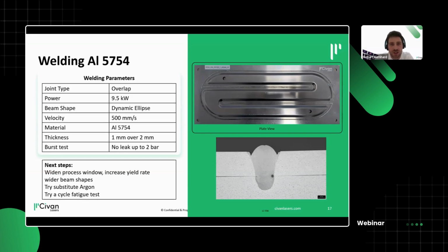So there are, of course, some challenges to overcome at these high speeds. And I would argue that we can even widen the process window to get rid of undercuts. But in general, it's really important for us to have the leak tightness, and this is what we are able to achieve with this parameter set. I'm of the opinion that we can also do construction or structural welds as well, but the leak tightness here, the long welds we need, we are able to achieve at 500 millimeters per second.